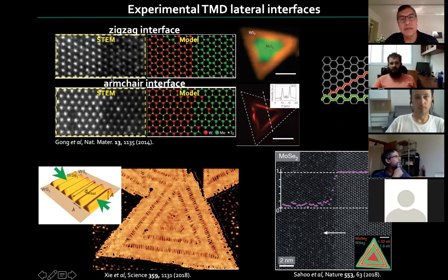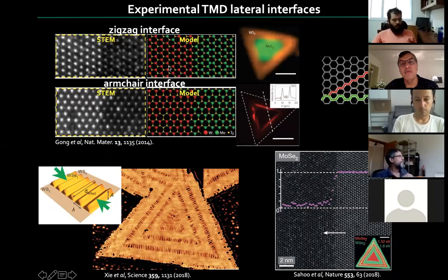Now, these are TEM images of such an interface. You see here the metal, because it's the one that is electronically dense. And so you can see that the shading changes because you're changing composition. So you go from tungsten on the left to moly sulfide on the right. In this case, they're changing metal. In all cases, it's sulfur, the other part of the material.